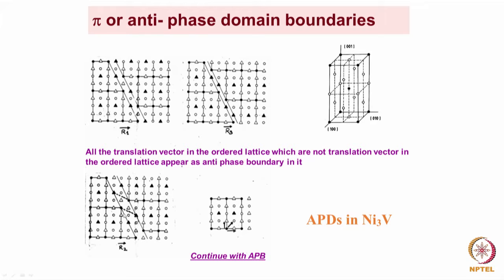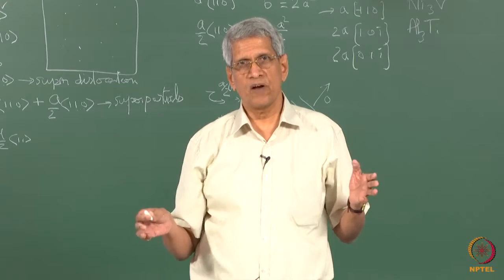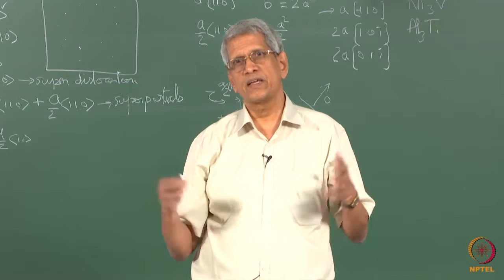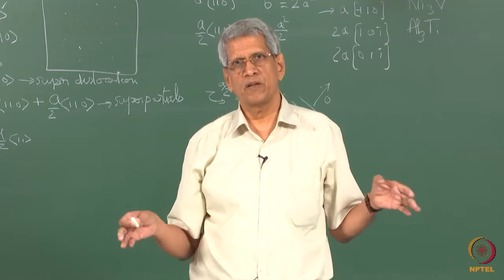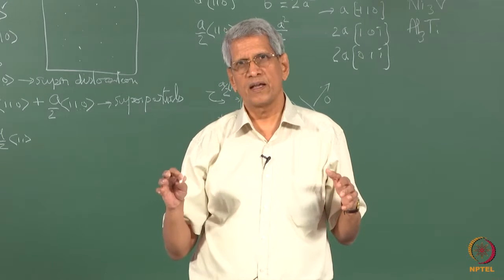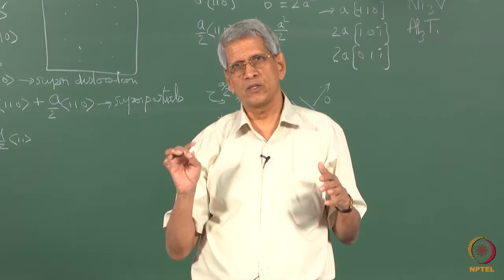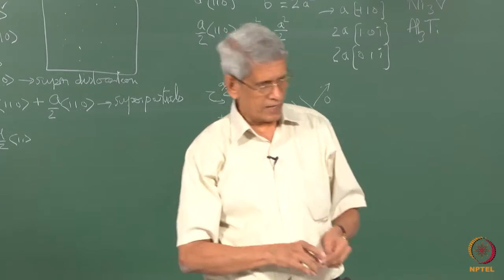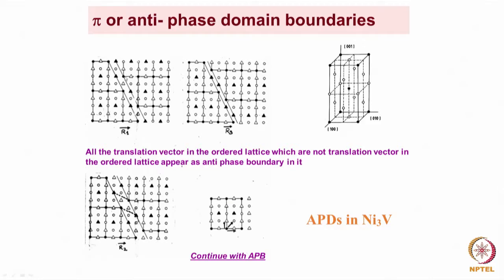All these structures which we are seeing now are essentially nothing but the structure of another phase, like in a stacking fault, where FCC stacking fault creates HCP structure. Similarly, an antiphase boundary also, because a superpartial passes through, will create a fault. The faulted region could correspond to a nuclei or the unit cell of another structure. That is what we can typically see in these cases, where a two-dimensional projection of the 3D lattice is being shown. This is shown along the 100 direction projection.